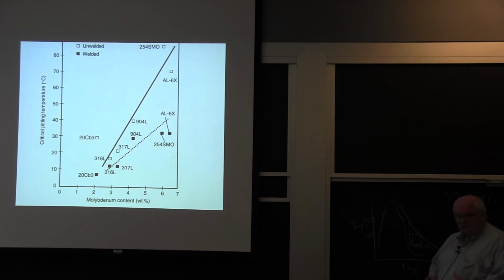When you weld it, because of segregation in the welding zone and changes in the welding microstructure, you'll get pitting at a lower temperature. If you add more molybdenum, you get 316, 317. Should have been a bigger change there, but in any case, about the best, and at temperatures, how hot does it get? About 37 degrees centigrade in the tropics in the seawater, doesn't it?